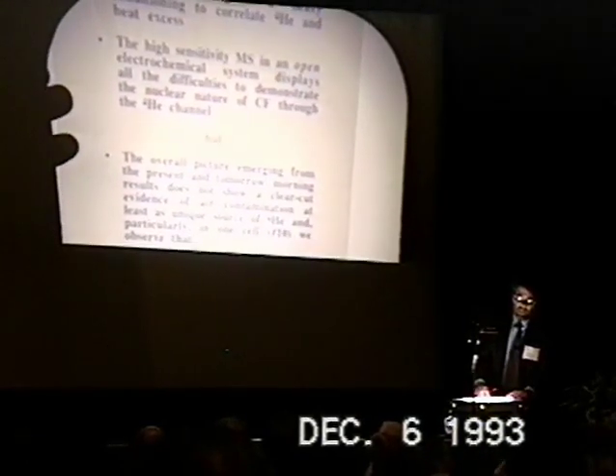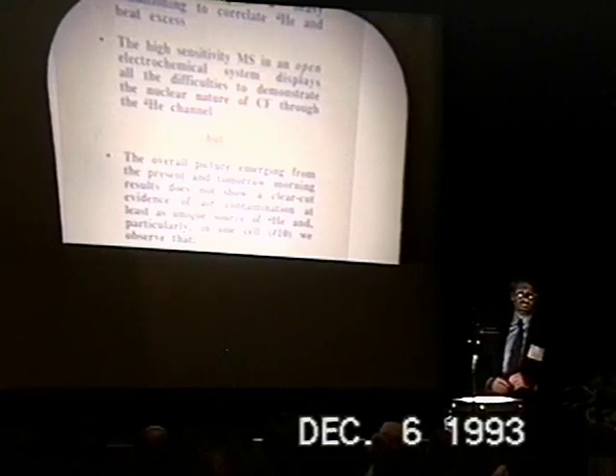But the overall picture emerging from the present and tomorrow morning results does not show a clear-cut evidence of air contamination, at least as the unique source of helium-4, and particularly in one cell, cell 10, we observe that the integrated heat excess from both the calorimetry and the helium-4 show a ratio close to 1. And the excess heat power from calorimetry is of the same order of magnitude as the excess heat power calculated from helium-4 data, even if there is not a strict time correlation between them. There is a clear evidence of excess heat followed by a sharp increase of helium-4.